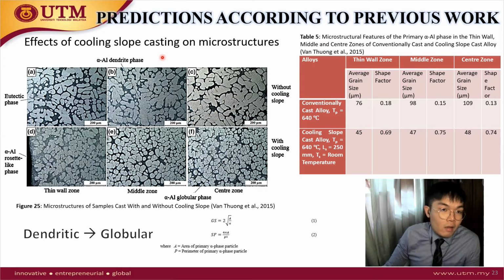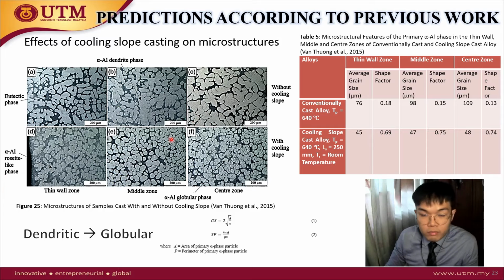First we look at the effect of cooling slope casting on microstructures. From figure 25, without cooling slope casting, you can see the microstructure is a dendrite structure, and with cooling slope, the dendrite structure has converted into a globular structure. This globular structure is quantified using equation 2, the shape factor equation. When the shape factor equals 1, it means a perfect circle, so closer to 1 means the globular structure is rounder. The results are summarized in this table. From the conventionally cast 0.18 shape factor, we can get up to 0.75 shape factor.